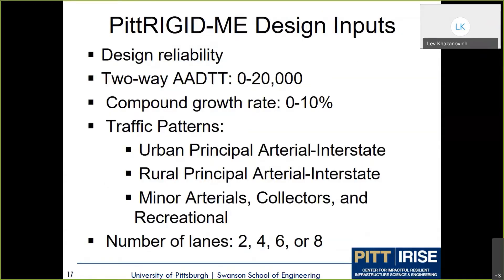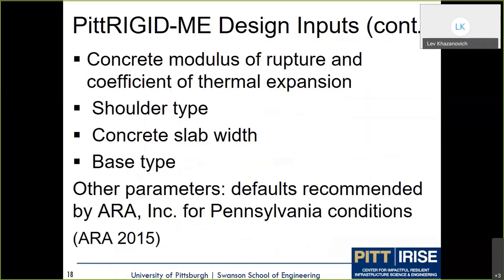Analysis of base type shows that use of a stabilized base may significantly affect predicted damage level, whereas the effect of base thickness is not as significant. Based on the sensitivity study results, the team selected values or ranges of Pavement ME inputs to be fixed in PitRigid, or identified ranges of certain values adjustable by the user — such as design reliability level, daily truck traffic volume, compound growth rate, traffic patterns, number of lanes, concrete modulus of rupture, coefficient of thermal expansion, shoulder type, and slab width.